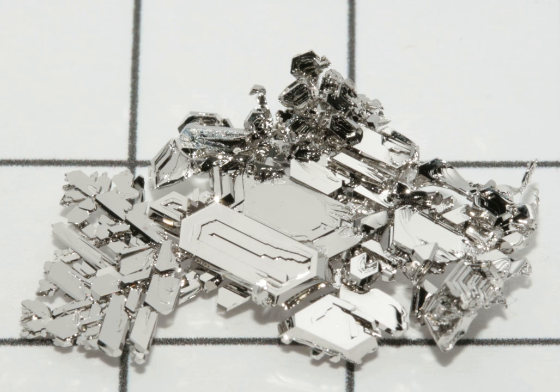195Pt satellite peaks are often observed in 1H and 31P NMR spectroscopy, i.e., Pt phosphine and Pt alkyl complexes. 190Pt is the least abundant at only 0.01%. Of the naturally occurring isotopes, only 190Pt is unstable, though it decays with a half-life of 6.5 × 10^11 years, causing an activity of 15 becquerels per kilogram of natural platinum. 198Pt can undergo alpha decay, but its decay has never been observed. The half-life is known to be longer than 3.2 × 10^14 years, therefore, it is considered stable.